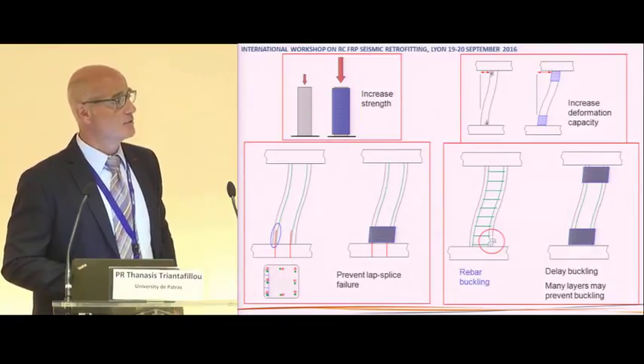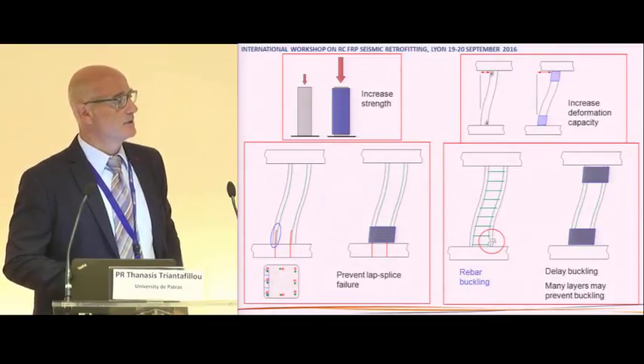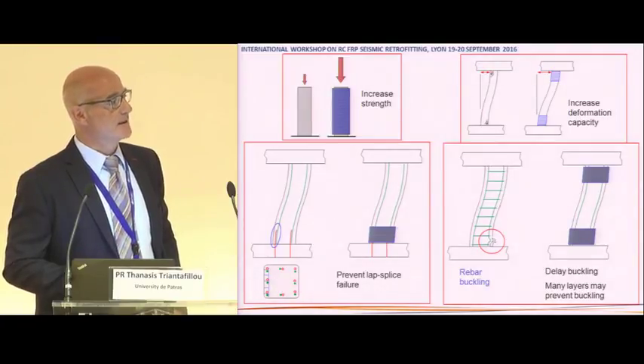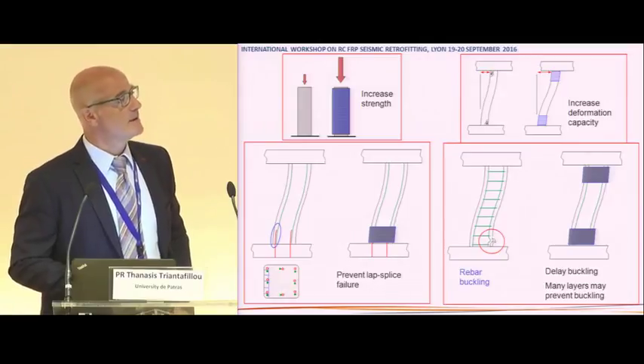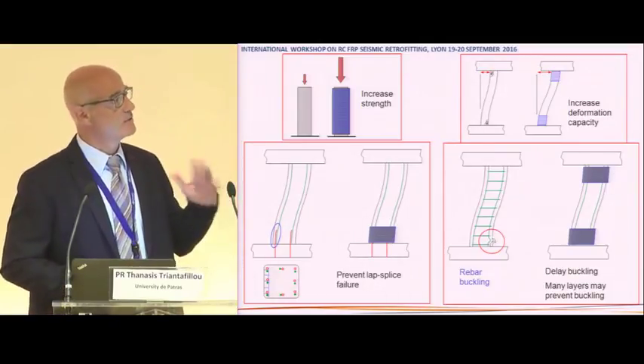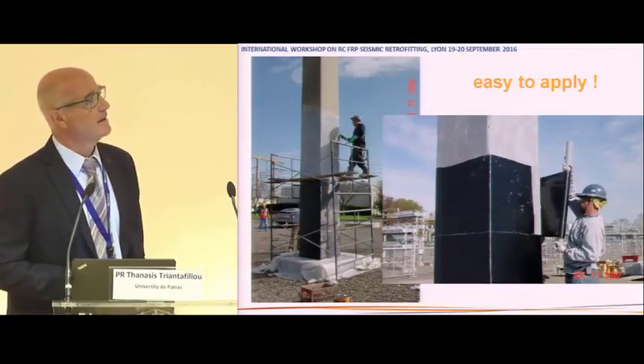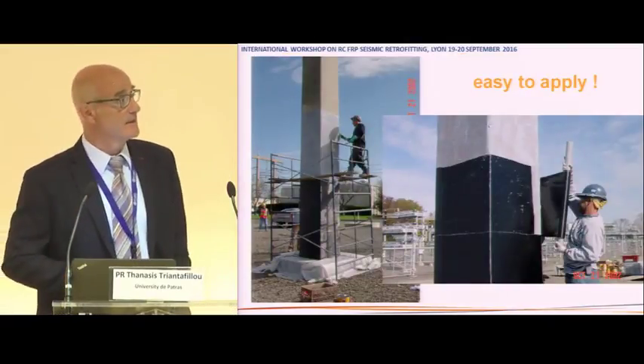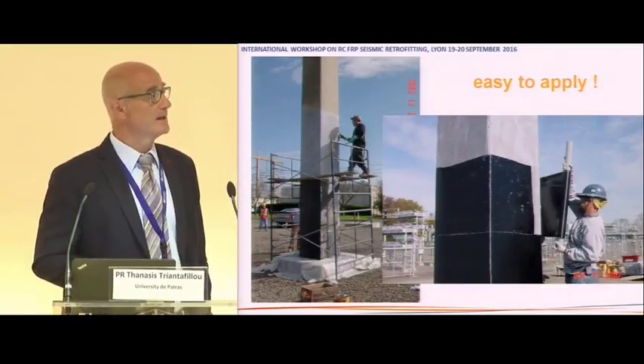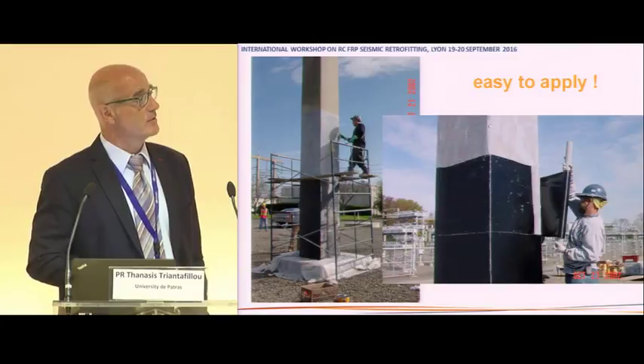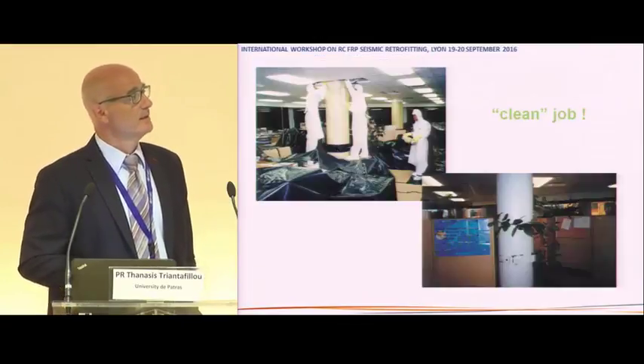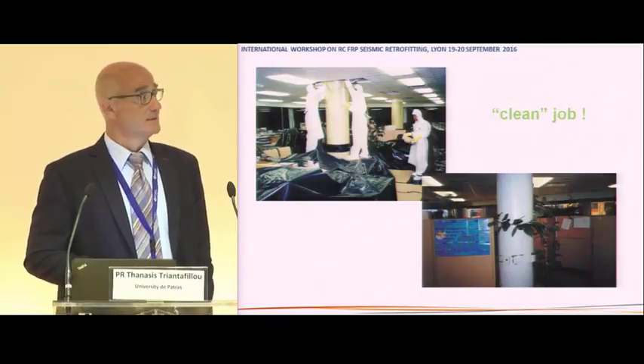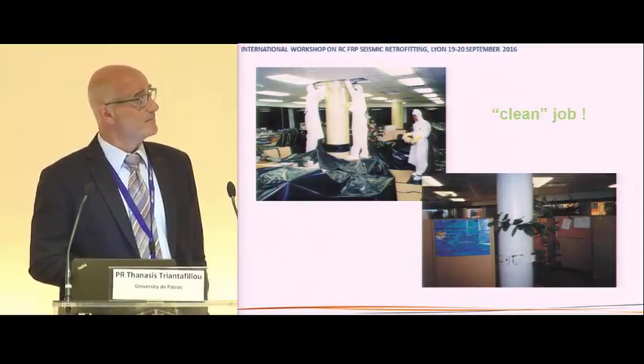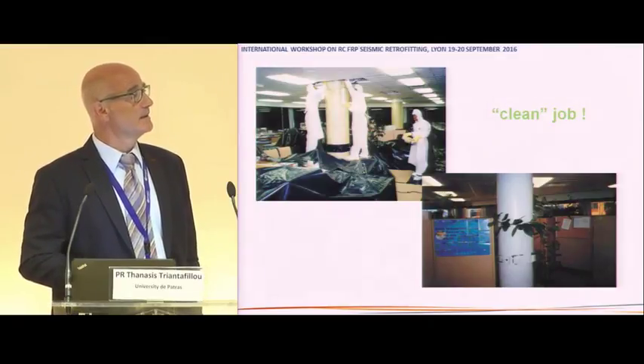We do this local jacketing also to prevent failures at lap splices and also to delay or even eliminate local buckling of the longitudinal reinforcement if our stirrups are at a relatively large spacing. So those are the basic reasons why confinement is done by FRPs. And why FRPs as confining elements? They are very easy to apply. This is the proof, that's a huge column and everything is done by a single person. It's a relatively clean job. We don't really disturb the occupants in buildings.